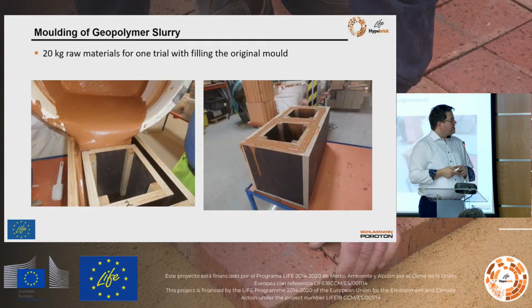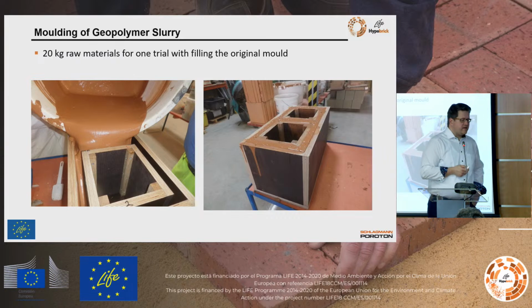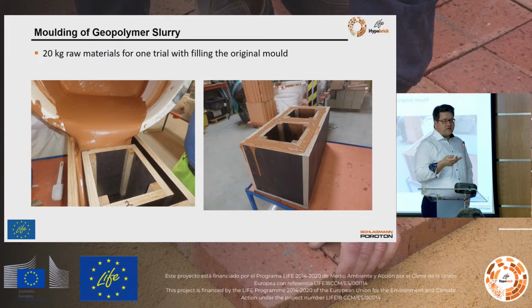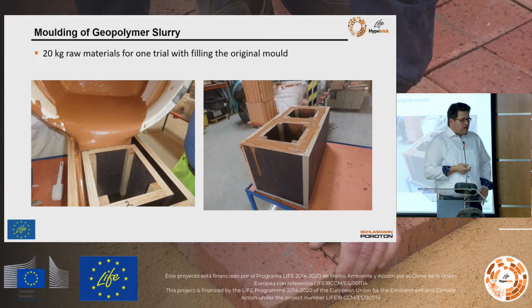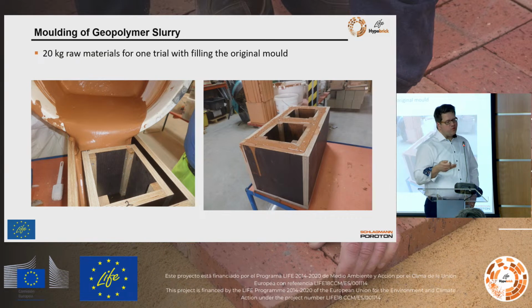So for that we shifted to molding our geopolymer paste, maybe then more a slurry, adding some water and filling these molds. And this is the original size of the geopolymer brick, to mimic the exact geometry, at least from the outer walls, the size of the classical clay-based brick.